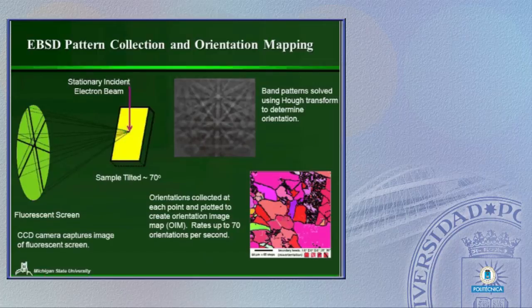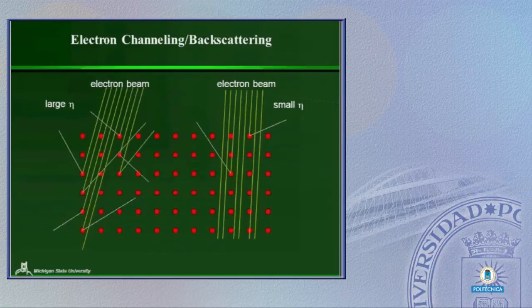And so we can do maps like this, and actually this is not accurate now. This is a few years old. This is rates up to 70 orientations per second. This is more like about 500 orientations per second if everything is now working correctly. But more what I'm going to focus on is this idea of electron channeling. With electron channeling, what we have is a situation that simply, as the electron beam orientation changes, or if the electron beam orientation remains the same but the crystal orientation changes, the backscattered intensity is going to change. And so there's a number of different ways that can be used to give us information about our sample.